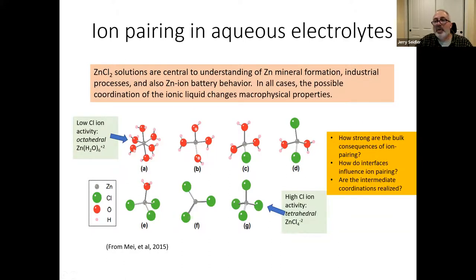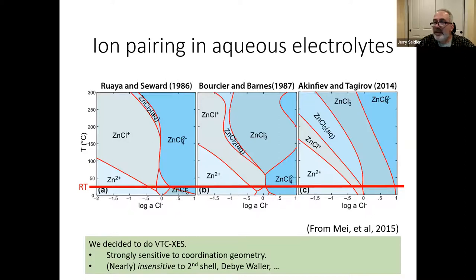how strong are the bulk consequences of ion pairing? How do interfaces influence ion pairing? And are these intermediate coordinations realized? So there's a significant literature on these intermediate coordinations, and in particular on the zinc chloride system. And you can see here, there's three different theoretical approaches, and they actually have a rather dramatic disagreement about what the equilibrium diagram and the equilibrium constants for these different intermediate moieties should look like.